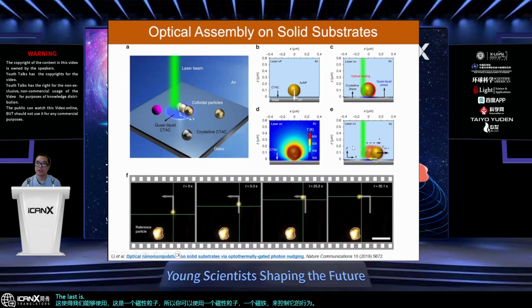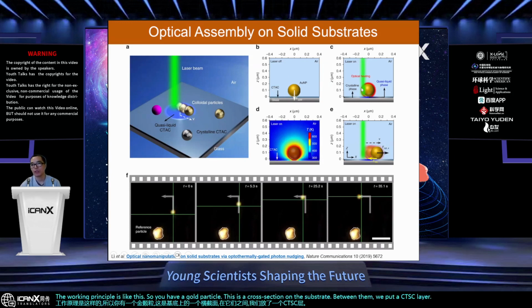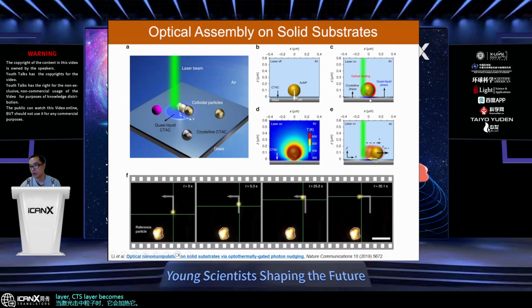The last scenario, the third one, is to show that using thermal effects, we can expand the working environment. So we can move the manipulation from solution to the substrate. Here I show you what we call optothermally gated photon nudging to achieve manipulation of particles on a solid substrate. The working principle is like this. You have a gold particle, this is a cross section, on the substrate. Between them, we put a CTAC layer. When the laser beam hits the particle, it gets heated up. So this CTAC layer becomes a viscous liquid phase. So the friction between the particle and substrate becomes weaker. So we can use a scattering force from the laser beam to push the particle.